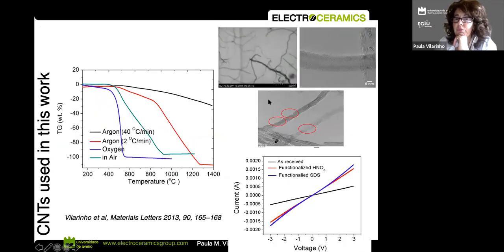So the first thing we did was really trying to see the thermal behavior of our carbon nanotubes, just to be able to understand if we can coat them with an oxide and then do a thermal treatment of this oxide. And what we observe is that if we deal with carbon nanotubes in a reducing atmosphere, they will keep being carbon nanotubes until a very high temperature. I think that's a very nice result. We have this publication here. This has been quite well cited, in which we really present the behavior in the different atmospheres and conditions in which we can keep the carbon nanotubes as intact as much as we can. And that's a relevant result.